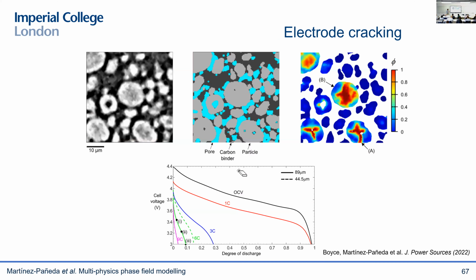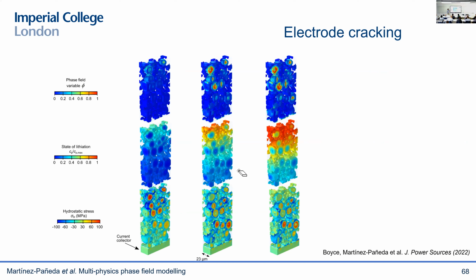And again, computers are big enough, so we can do both 2D and 3D. We can map those X-ray CT images, do segmentation, and then introduce this into our finite element model. You can see here some 3D predictions of cracks evolving as a function of time. So we can see, for example, what is the effect of electrode thickness or the voltage window, and so on and so forth. Again, the same idea, using a virtual platform to accelerate the development of reliable lithium-ion batteries.